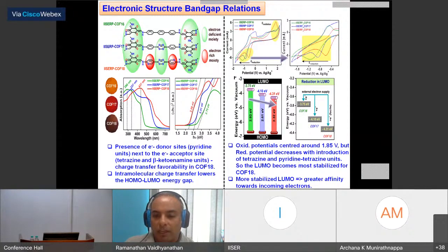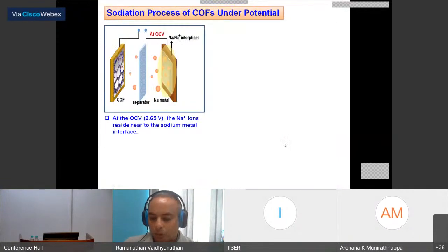But what is the overall effect? You have decreased the HOMO-LUMO gap in the pyridine plus tetrazine compound. And this is also shown here very nicely. So the COF, which has both the tetrazine groups and the pyridyl groups, has the lowest LUMO level as well as the lowest HOMO-LUMO gap. So this is a modular approach to achieving this. Now, what does this do to the anodic characteristics?